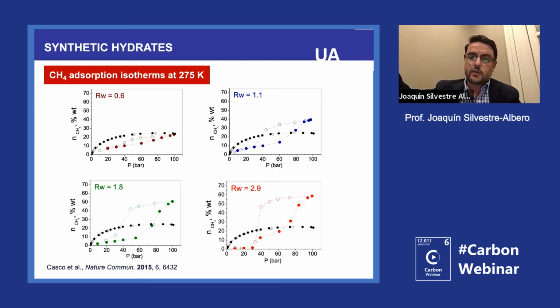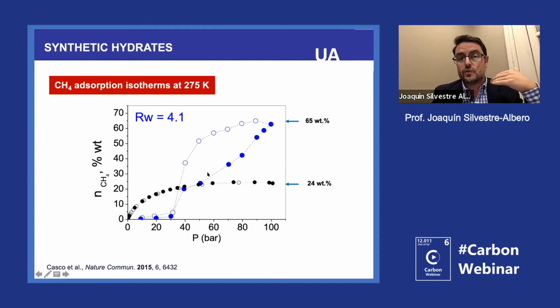And the nice thing is that when we were doing the desorption, there was a very significant hysteresis loop. So something is happening in the cavities of the carbon when we incorporate water and high pressure methane. Even when we went to this oversaturated sample with 4.1 grams per gram, you see that we have a similar performance. So we have blocking, a jump at the beginning, and then we have this progressive increase until we reach 100 bars. And the nice thing is that we are able to improve the storage capacity of the system for methane from 24% to 65%.